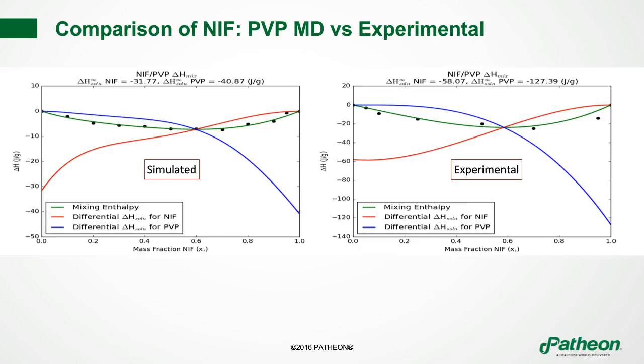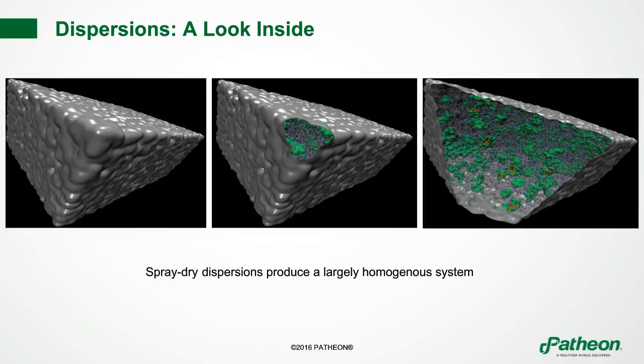All right, so moving forward, what you see here is just a look inside what these dispersions actually look like. On the left is just the surface of a brick of the PVP and nifedipine, and then in the middle I'm starting to cut away, and then you can see on the right that the green blobs with little bits of orange are the actual drug molecules, and this is about a 40% loaded situation here. The green blobs are the drug molecule, and then you can see the lighter bluish color in sticks are the actual polymer. And what you see is a very, very homogeneous system. And I might add that spray-dried dispersions produce this homogeneous system by and large most of the time.